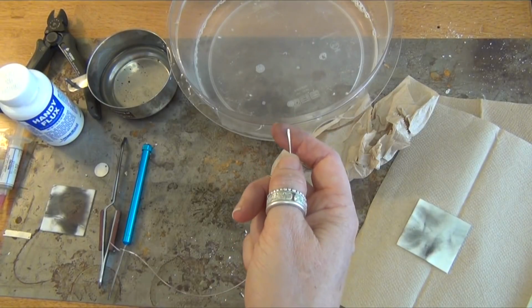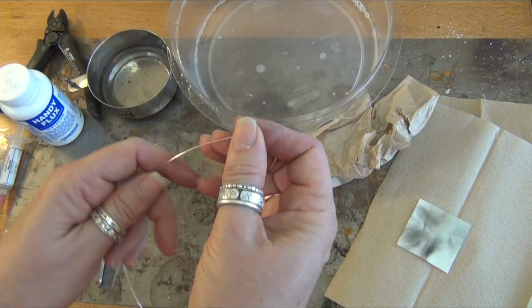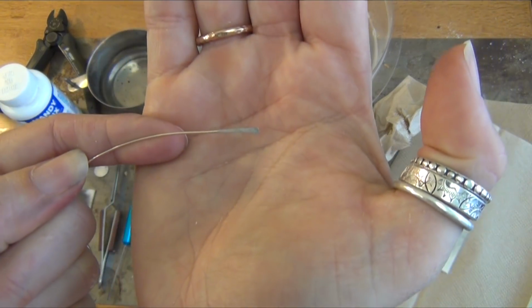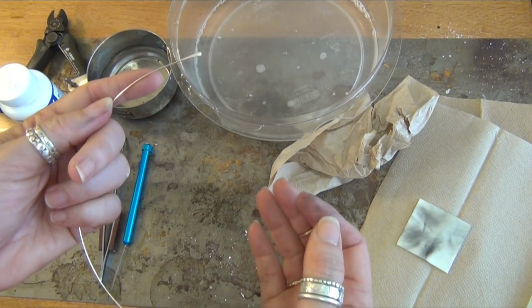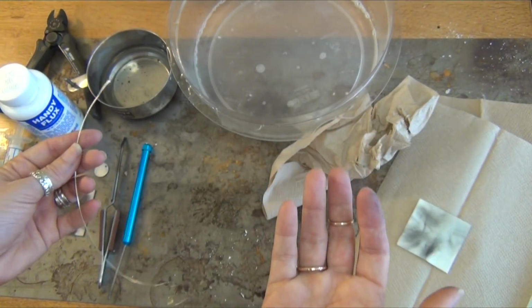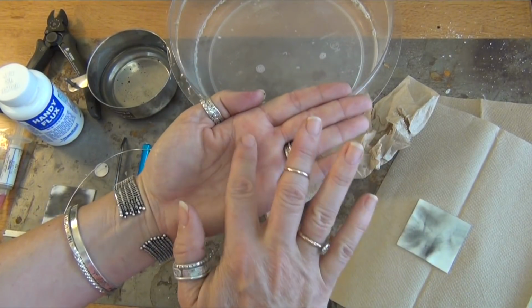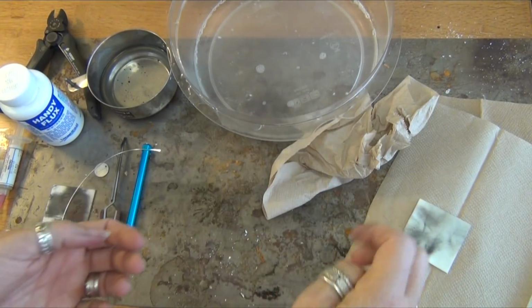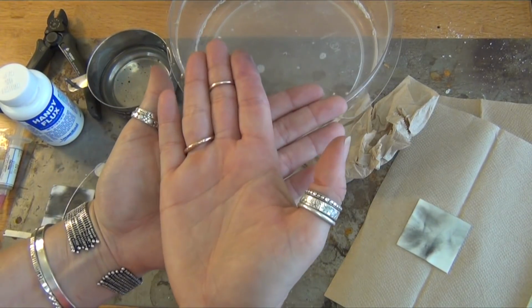There's a couple different ways to do it. You can sweat solder, you can pick solder it on, but what I think works well with something where you're just soldering something flat to something flat, is I take the tip of the solder wire and hammer it. So can you see here that it's kind of flat? And then cut it so I have a flat piece of wire, a pallion, and you can also do this with solder sheet. It would be probably about a quarter of a millimeter, a really small piece depending what I'm soldering. Now I'd put it on the blank that I'm soldering to. So blank, flux, little piece of wire solder, thing I'm soldering on top. And then what's fun is when you torch it and you solder it, the piece actually drops because it's on this larger piece of solder.